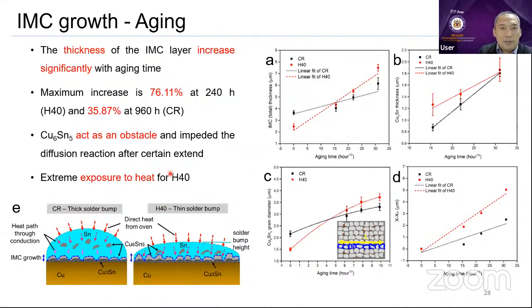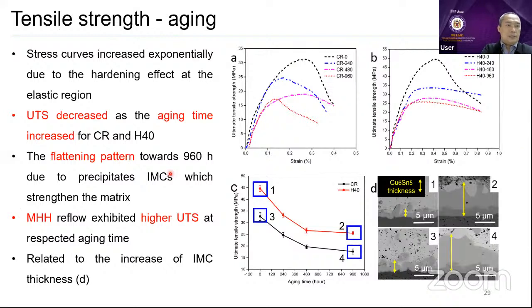Sorry, I need to go directly to the tensile. The comparison between the microwave and the conventional one. For sure, because we had a very thick IMC, it can give us a much higher strength. You can see here, it can reach about 50 compared to the conventional, which is about 30 megapascal. That means it is a very good tensile property.